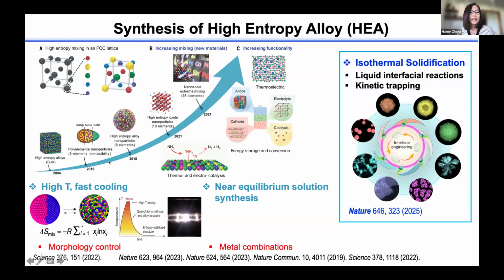These types of approaches have the drawbacks of being hard to control the morphology, or they are intrinsically applicable only to thermodynamically miscible combinations. We created a new type of approach inspired by our liquid phase TEM observation. I'm going to show you this new synthesis strategy, which is called isothermal solidification.